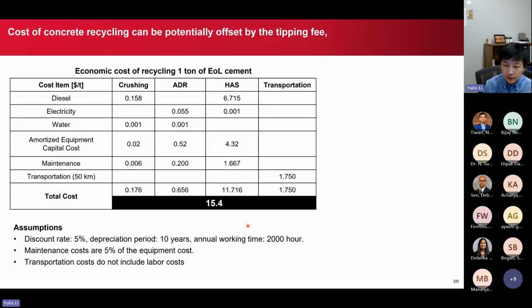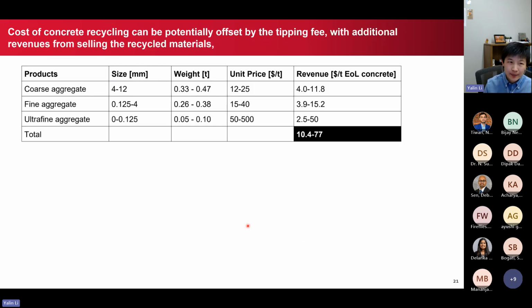And then right now, there are concrete recycling facilities, and they charge a tipping fee of around $10 to $15 per ton to help you recycle or get rid of your concrete waste. So the tipping fee can pretty much cover the cost of this recycling part, but there are also some economic benefits from this, because we're now using these technologies. You will have the coarse, fine, and ultra fine aggregates that can be reused when you are making new concrete. And then depending on how pure your products can be, the economic benefits from recycling can be $10 to $70+ per ton. So this essentially means you could benefit economically from using such processes to recycle your concrete.